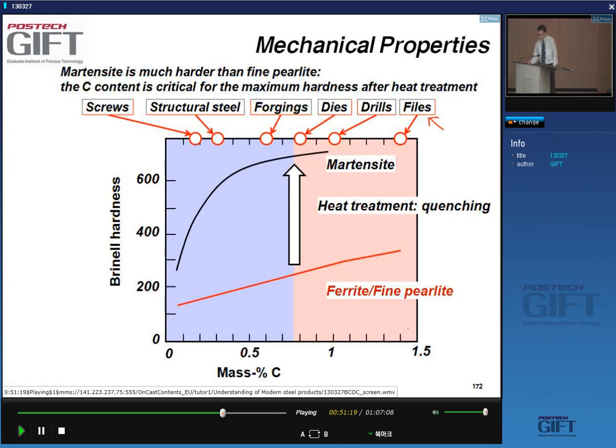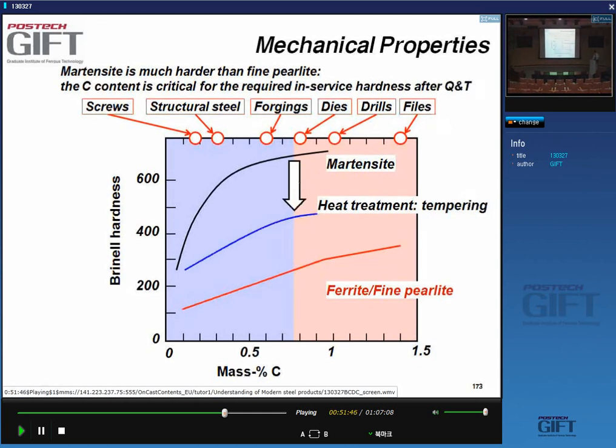You see that what we will do is we will harden the material by having very hard martensite where we have a large amount of carbon in supersaturation. We do this by quenching. However, as we obtain this very hard martensite, our material is not very tough. That means it is not very resistant to crack propagation,